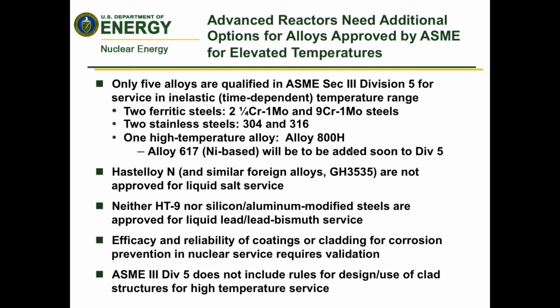And there are a number of materials that have been evaluated for liquid lead service, particularly the high silicon and high aluminum modified steels, which seem to have higher corrosion resistance in liquid lead, but they also are not approved for construction in ASME code. A couple of approaches that have been proposed are to take some of the existing materials, such as the stainless steels or alloy 800H or even 617 once it's approved, and coat those with a corrosion-resistant material such as nickel for liquid salt service, or even Hastelloy N as a clad layer.